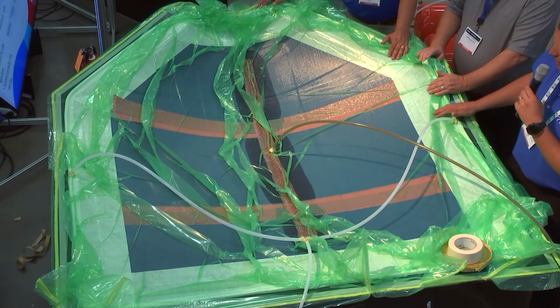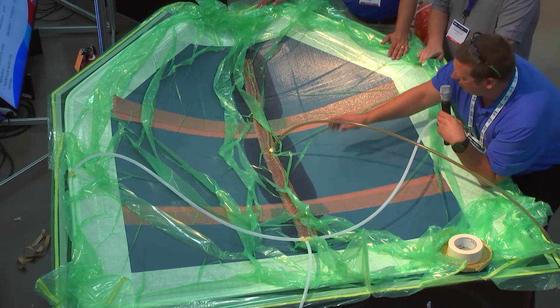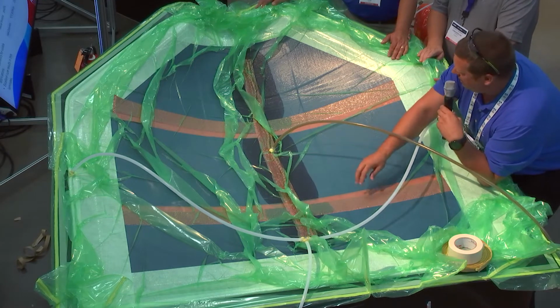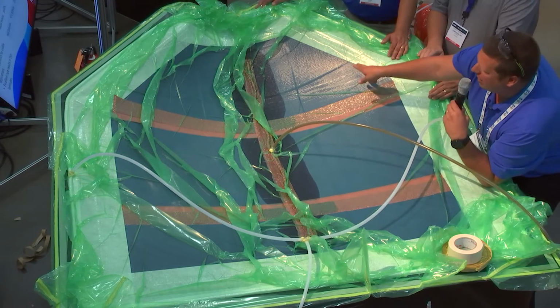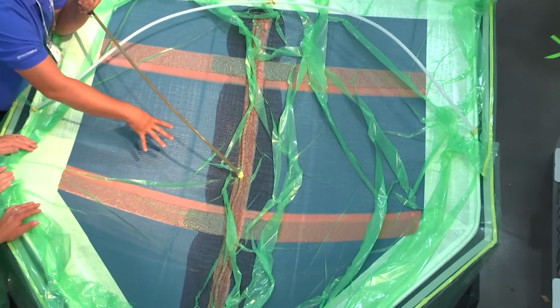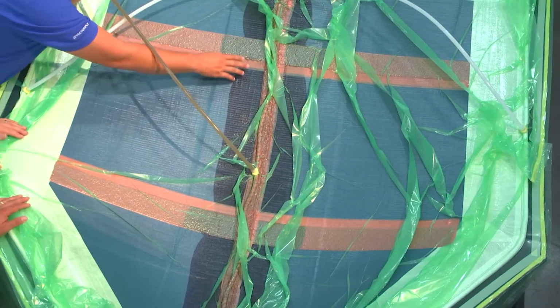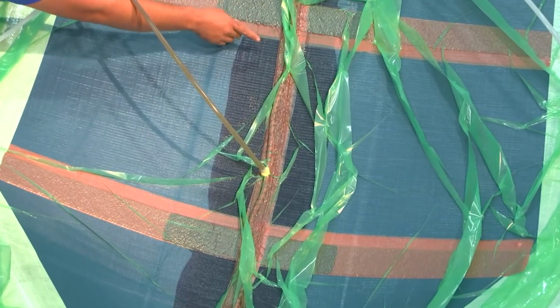Yeah, so you can see here the brown 2.0 material. As the resin came in this tube here, it distributed quickly along the long axis of the part. And now it's starting to bleed out into the laminate. And you'll see the resin is starting to transition from the brown material into our branches here, which is the orange 2.0.